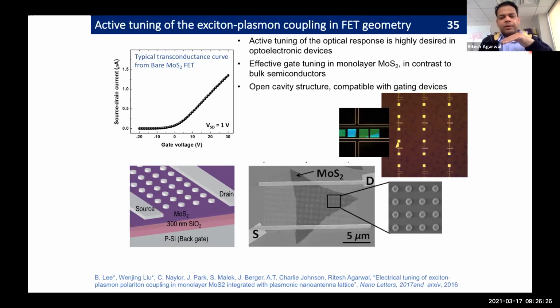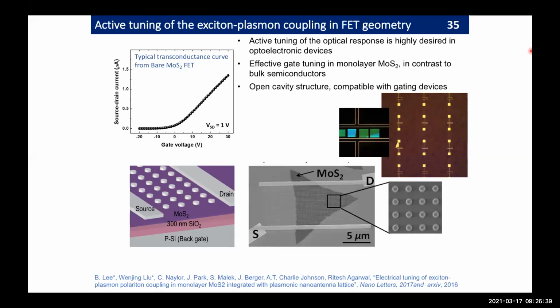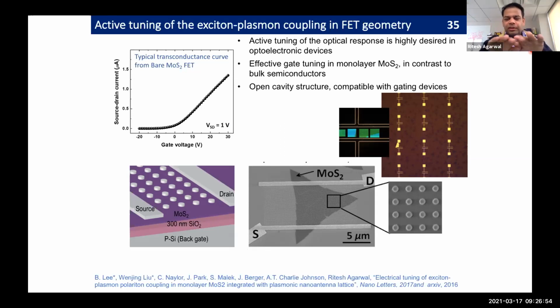So in this transistor in general, what we have is a silicon oxide, and then the two-dimensional material, and then the plasmonic cavity is patterned on top of the 2D material. So there is 2D material in between the nanoparticles. In those spaces between the nanoparticles, there is also MoS2. So it's a 2D extended system, and then on top we pattern these plasmonic particles. Okay, I think that answers my question.